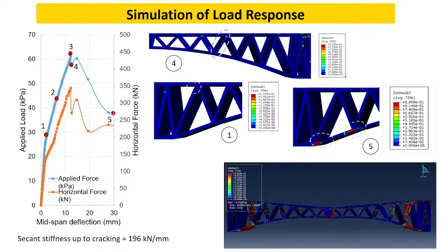Now, if you look at the damage in the bridge, you see that most of it is tensile. So basically, the tensile members, the diagonal members, crack first, and that little bit of residual stress that the wire is able to provide basically redistributes the forces within the lattice. So you don't need a whole lot of tensile capacity to be able to redistribute forces within the structure.